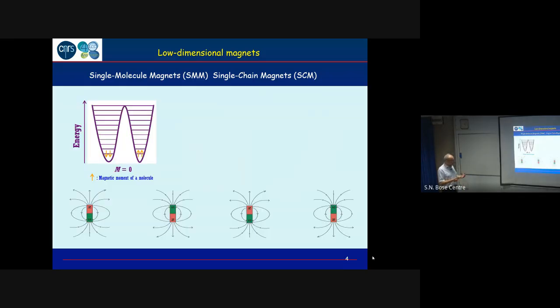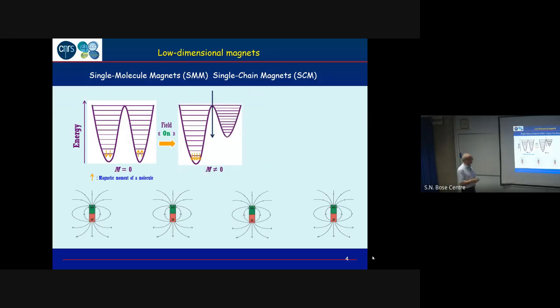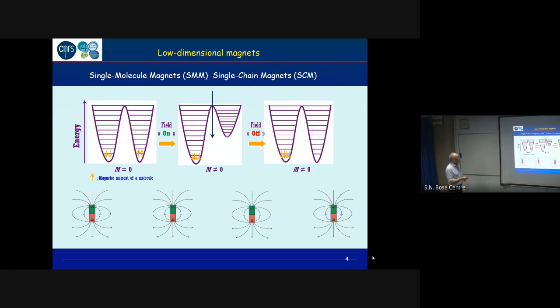If now you have an assembly of such molecules, you have a random orientation of the magnetic moment of each of these species. A way of drawing that is like this, which means you have as many moments oriented in one direction as in the other direction. But if you apply a field, you can turn all your molecules so that the magnetic moments are oriented in the same direction. When you switch off the field, this is supposed to stay like that. So your system gets magnetized, at least as long as the temperature is below a blocking temperature.